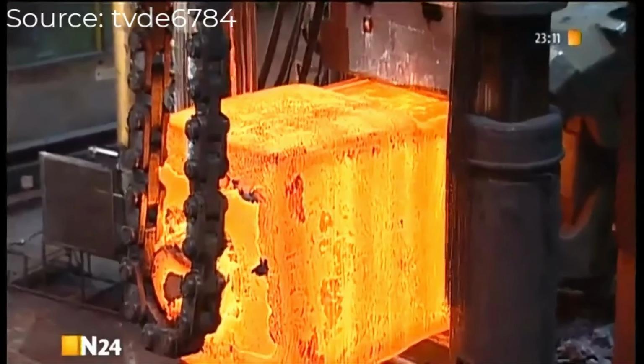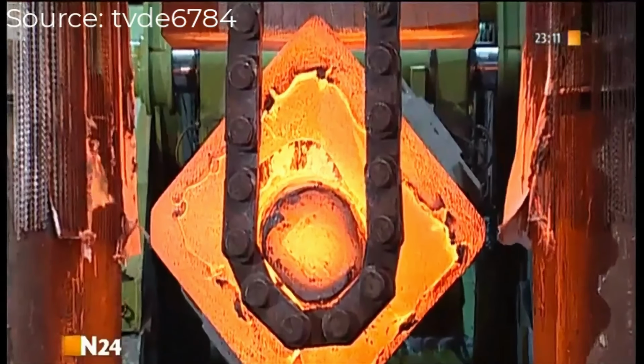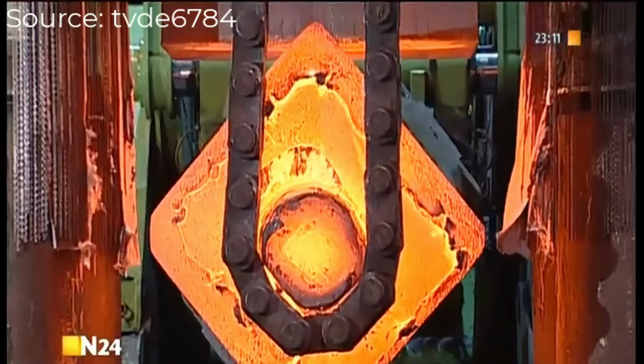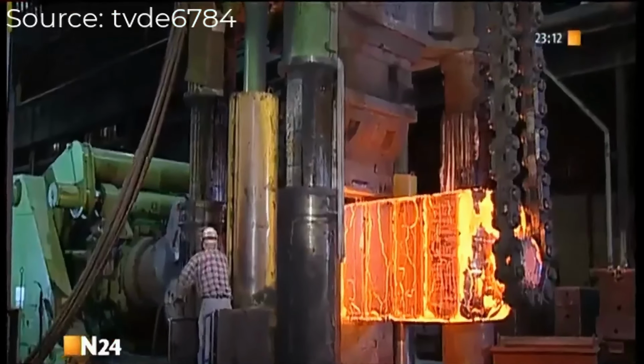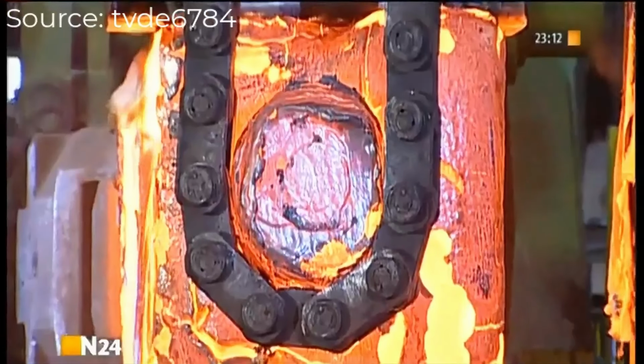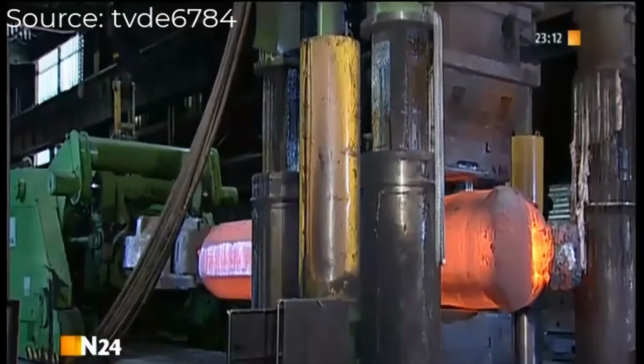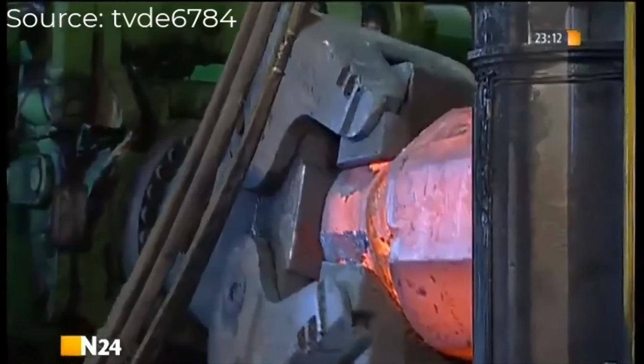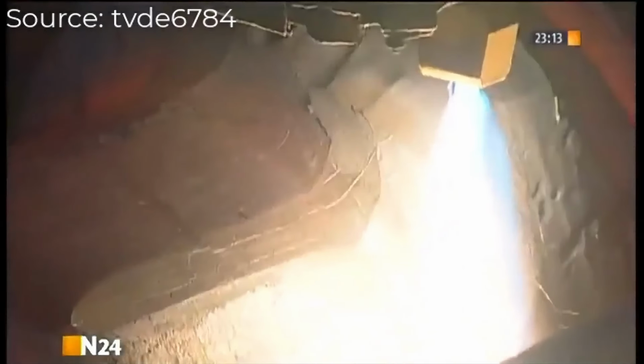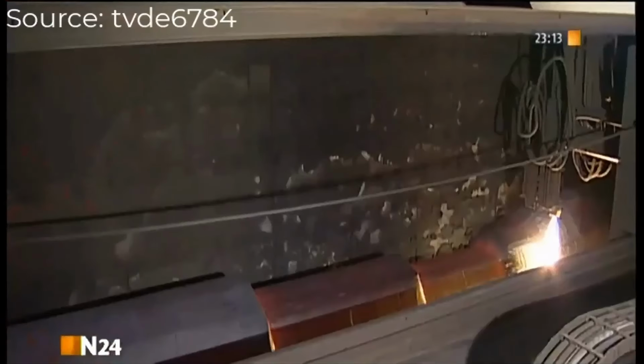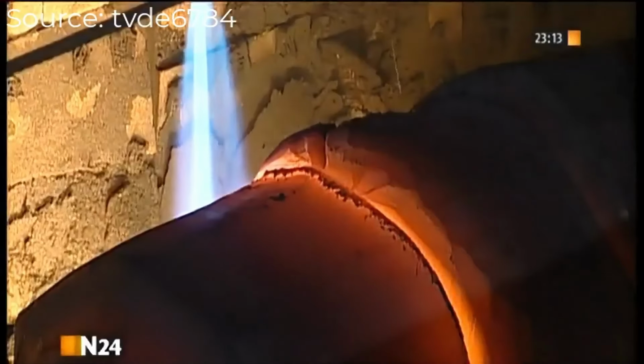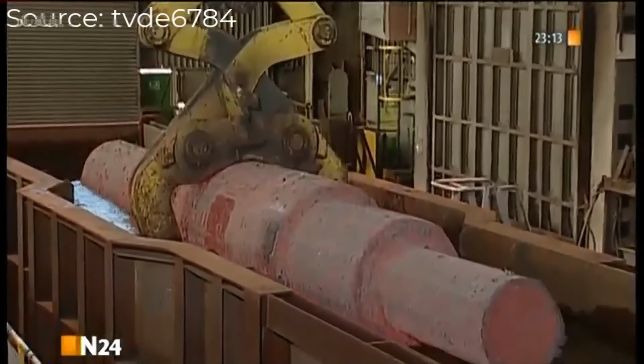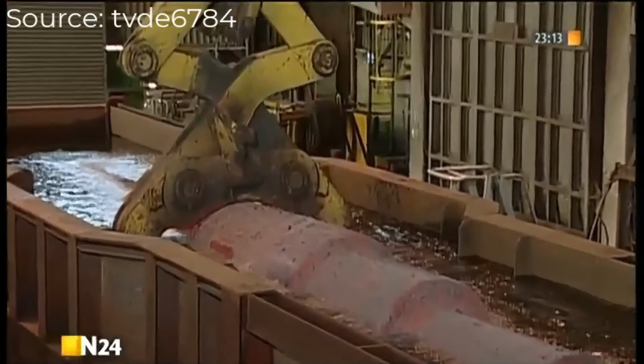After multiple heating and pressing cycles, the shaft is hardened in a water bath. Precision machining removes up to 14 centimeters of steel, achieving accuracy within half a millimeter. Producing over 200 shafts annually, Saarschmied blends high-tech precision with backbreaking effort, with each shaft valued at around 200,000 euros.